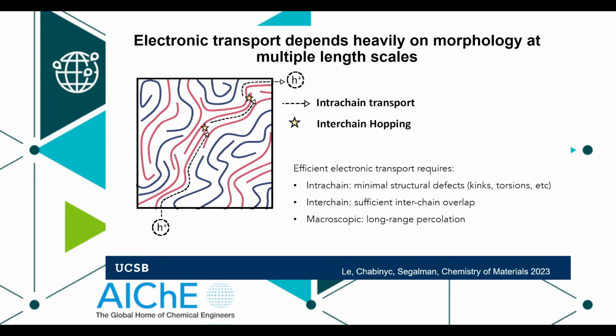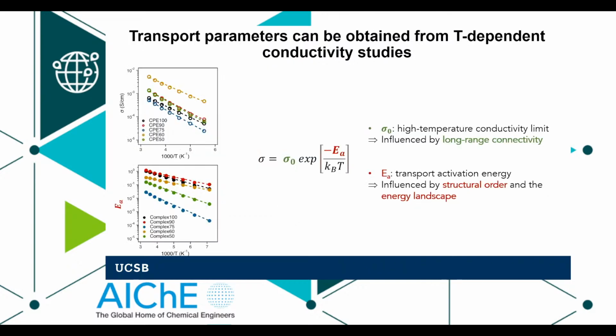All of these things have to line up to give us that kind of high performance across lots and lots of length scales. And we can actually probe that. One way to do that is doing temperature-dependent conductivity. The prefactor tells you about the high temperature conductivity limit, which tells you about the long-range connectivity of your system. The exponential, the activation energy, is telling you about the structural order. How well are the chains aligned? What is the conjugation length within them?